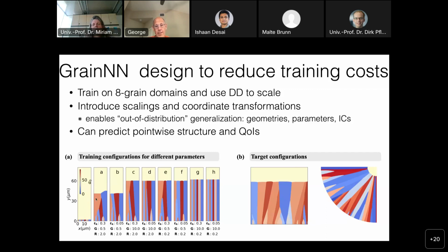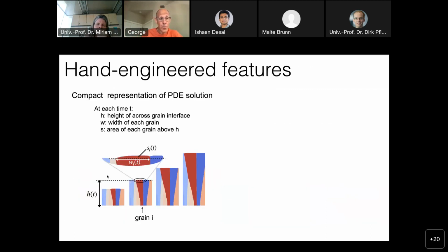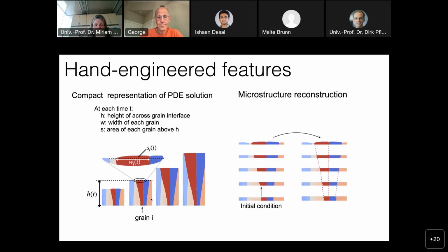So instead what we do, we use the nature of the problem that essentially we have what's called epitaxial growth, in which the grains grow following the temperature gradient. And instead we have these manual features in which instead of representing the whole thing as an image, what we represent is the current height of the solid liquid interface. For every grain, we store the width of the grain at the top, at the solid liquid interface, and some excess area because the interface is not completely flat. So we're not going to resolve these complicated shapes here, but instead we're going to represent the scalar variable that says how much extra area is on top of the average solid liquid interface. And these will be functions of time and will be for every grain. So this will be our manual features. So essentially the height, and for every grain, its width and excess area.